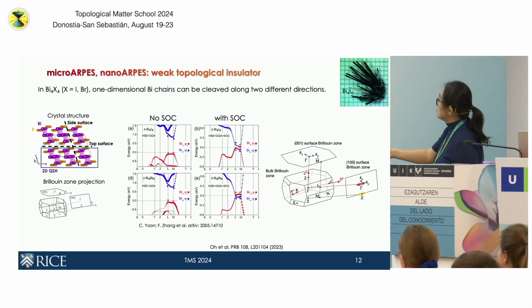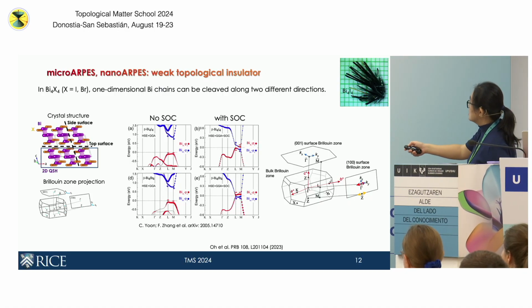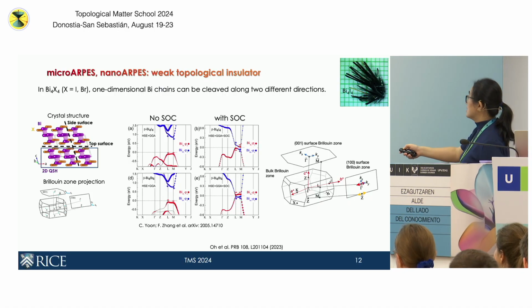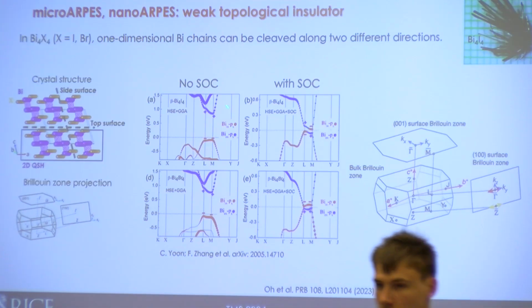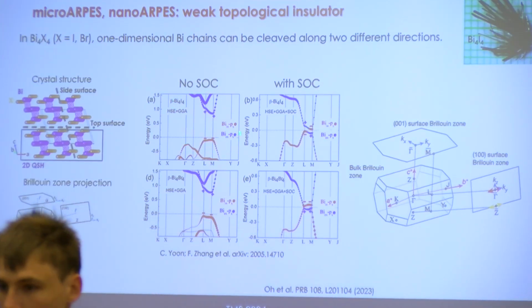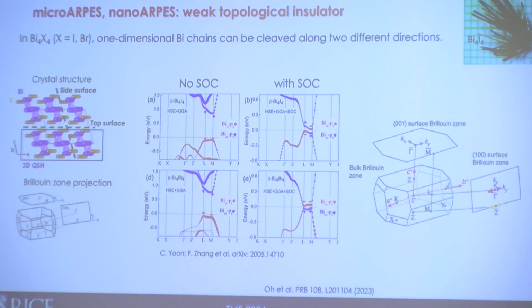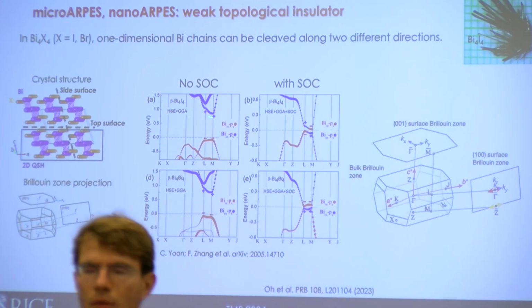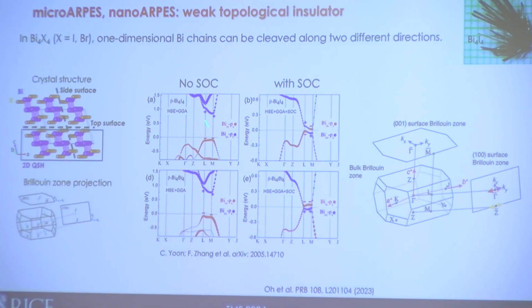And when you calculate the band dispersions of these materials with DFT, without SOC, this is the band that's closest to the Fermi level. And these are bismuth p orbitals. And the size of this gap actually strongly affects whether this eventually becomes a weak TI or a strong TI. And the reason is the following. So this is what's calculated for bismuth iodide. This is what's calculated for bismuth bromide.